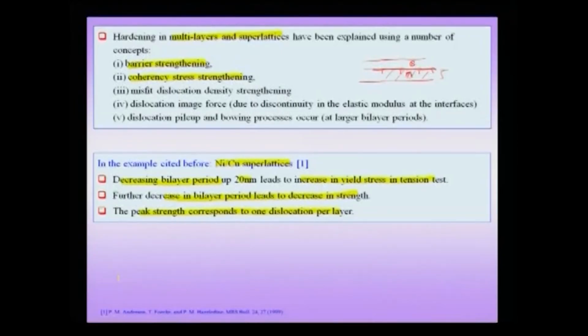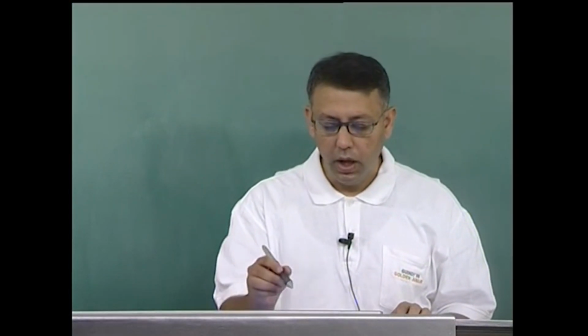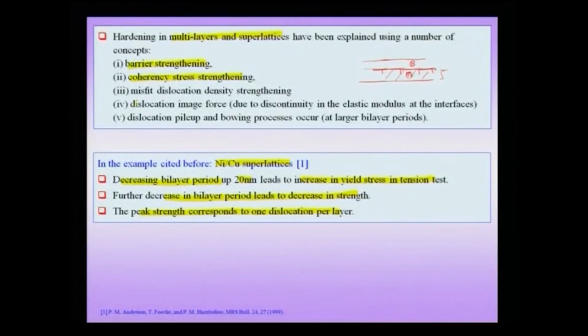It is not a statistically stored dislocation in the bulk of the crystal, and such a misfit dislocation would tend to give rise to a certain hardening effect, which could be attributed to the additional hardness of such a material in the nanoscale. Additionally, there is the concept of the dislocation image force, which we have encountered before, and this is due to the discontinuity in the elastic modulus at the interfaces.